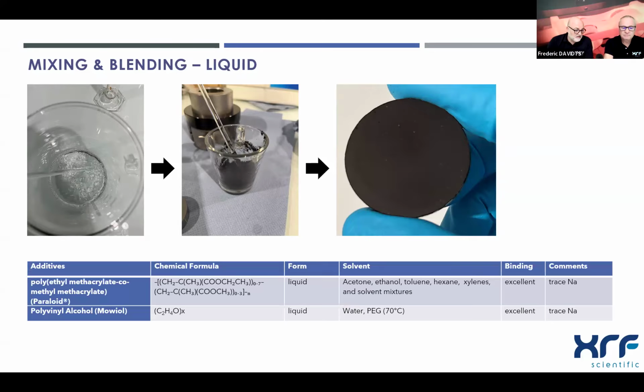really dusty. And if we can take two examples, we have the PMMA, so polymethyl methacrylate, and this is a very good compound. So it's first dissolved using a mix of solvent, could be acetone, ethanol, hexane, and the solution takes about 30 minutes to be prepared. But after, when you add that, let's say 2 milliliters, to the sample powder and mix well, it evaporates in 5 minutes. So you can directly press the dried powder and prepare the pressed pellets. And of course, we also have the Mowiol, which is also very well known. You can dissolve that in water or even in acetone, but it's a little bit longer.